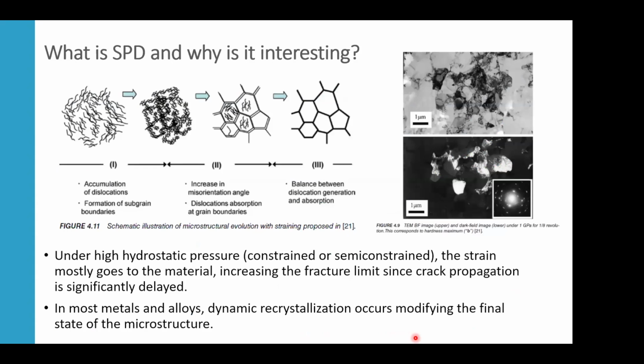So just to go a little bit deeper into what has been proposed and researched throughout the earlier years of severe plastic deformation: as I said, when we use hydrostatic pressure, most of the strain goes to the material, especially to shearing and creating a lot of crystalline defects, and does not change the overall shape of the workpiece. So in SPD, one of the criteria is that we should not significantly change the shape of the workpiece. By doing this, we can increase the pressure and introduce a lot of crystalline defects. And these crystalline defects will evolve with the amount of deformation, first into high density clusters, and these clusters will eventually form subgrain boundaries, and these subgrain boundaries will probably recrystallize into smaller grains.